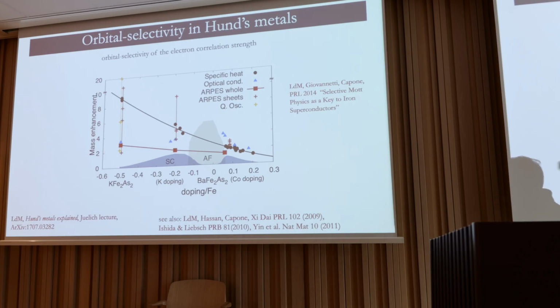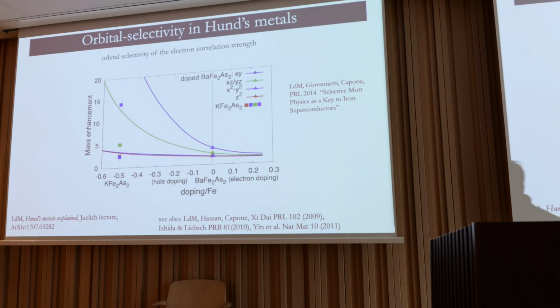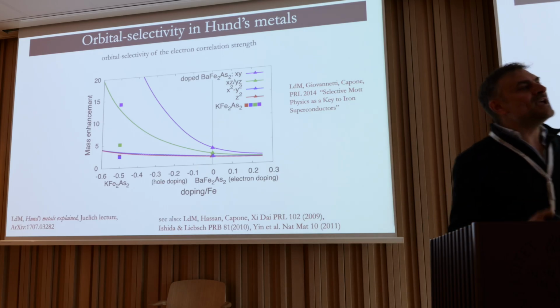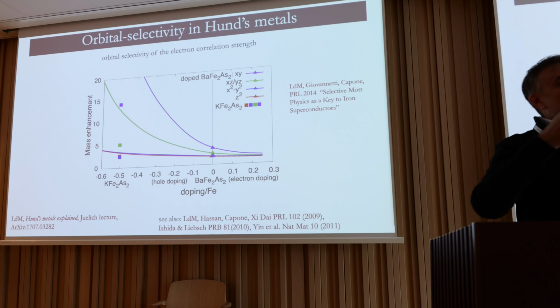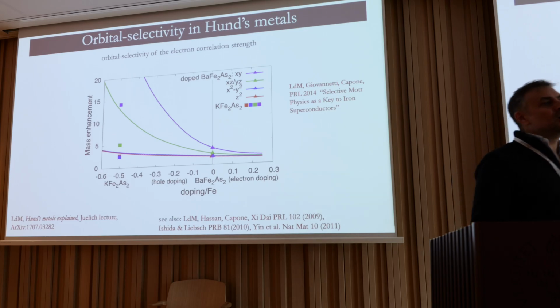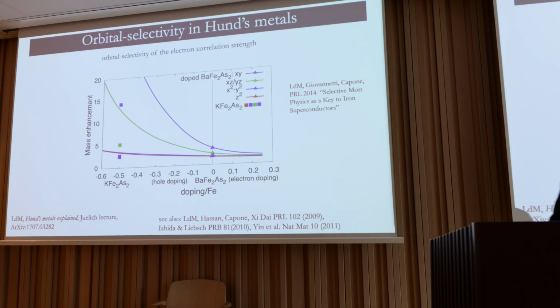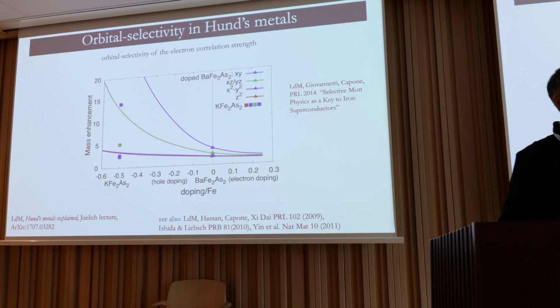Also, since these orbitals are all hopping into each other, there is hybridization between the light electrons and the heavy electrons. This is nicely captured by the same theory, the same DFT plus Slave Spin. If you resolve the mass by orbital character, you see some orbitals increasing slightly and some orbitals with correlations that really shoot up. So we have the d orbitals of iron playing the role of both the conduction electrons and the localized moments that you have in heavy fermions. Within the d shell, some orbitals play the role of the original f electrons in heavy fermions, and others keep playing the role of the conduction electrons.